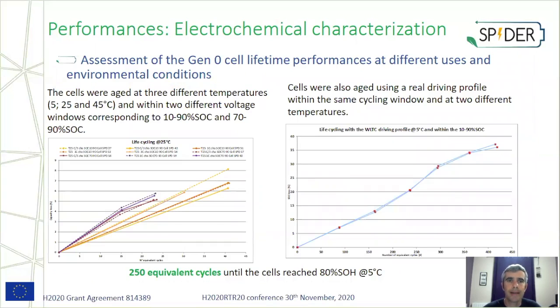In order to assess the Gen 0 cell lifetime performances at different uses and environmental conditions, we defined a test plan based on vehicle specifications and requirements regarding data collections for modeling. You have the capacity loss, which is plotted as a function of equivalent cycles calculated from the total capacity throughput divided by one cycle capacity. The cells were aged at 3 different temperatures within 2 different voltage windows, and using also a real driving profile within the same cycling window and at 2 different temperatures.